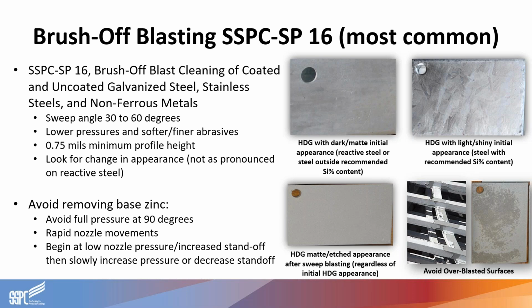What happens is you'll end up overblasting and removing a lot of the zinc thickness, sometimes all the way removed as well. This not only creates a rough surface condition, which is very difficult to paint afterwards, but it can also be quite difficult to repair in a way that doesn't impact the longevity of the project.